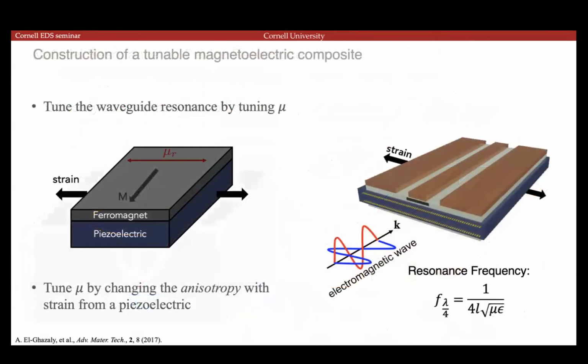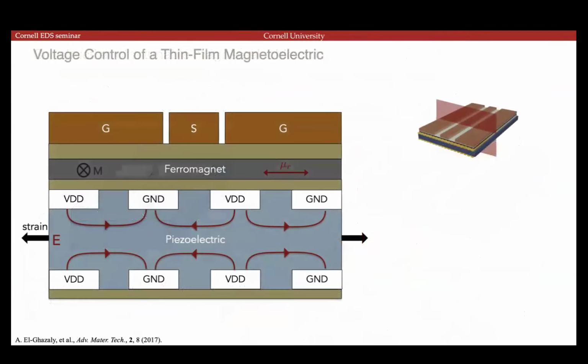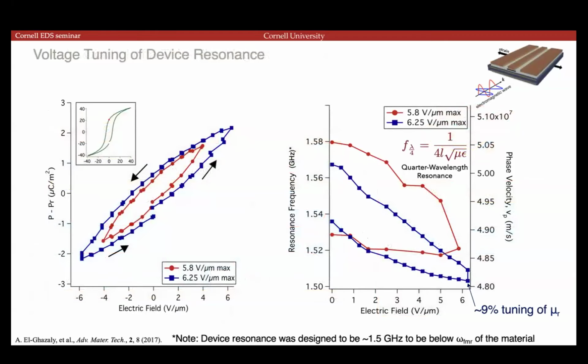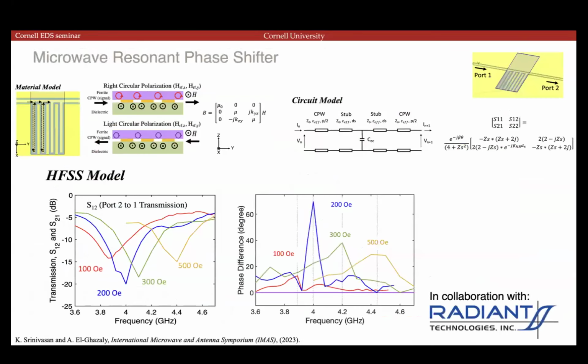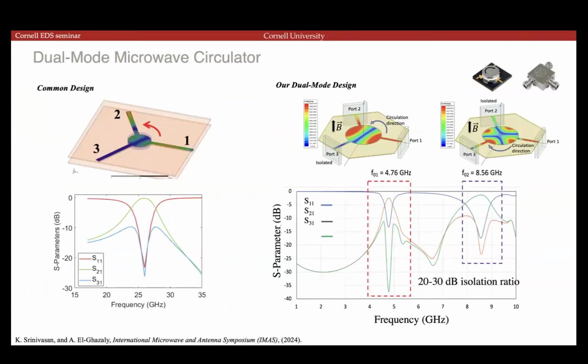The idea behind that would be to put a certain magnetic material that we've now designed and grown with the optimal ferromagnetic resonance frequency onto a piezoelectric, and then control the piezoelectric with voltage to strain the system. And that strain would couple to the magnetic material and change its resonance frequency and behavior. So these are some prior demonstrations from my previous work, and I'll leave it at that.